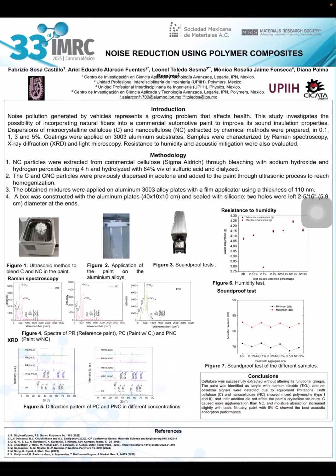The C and NC particles were previously dispersed in acetone and added to the paint through an ultrasonic process to reach homogenization. The obtained mixtures were applied on aluminum alloy plates with a film applicator using a thickness of 110 nanometers. A box was constructed with the aluminum plates and sealed with silicone. Two holes with a diameter of 5.9 centimeters were left at the ends. This is how we made our boxes to do the soundproof test.